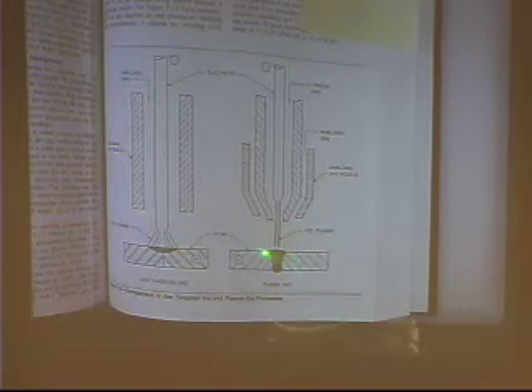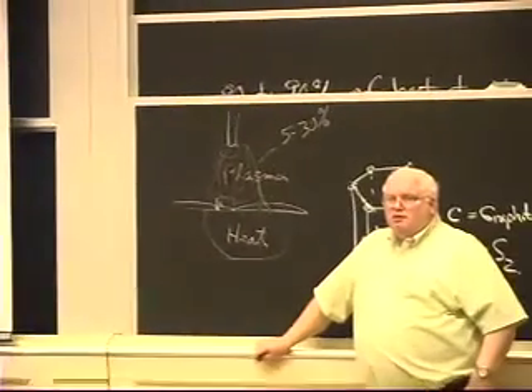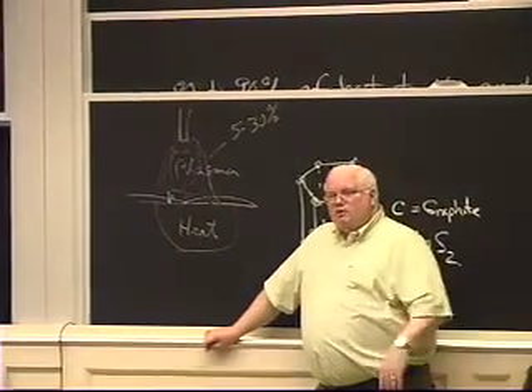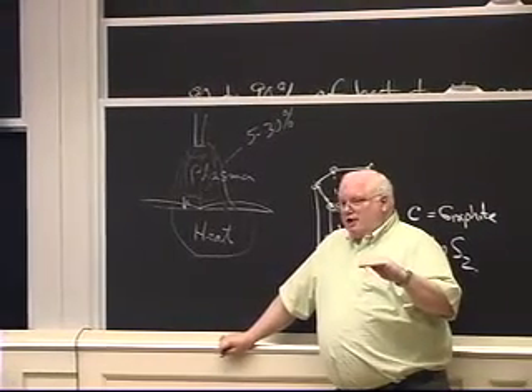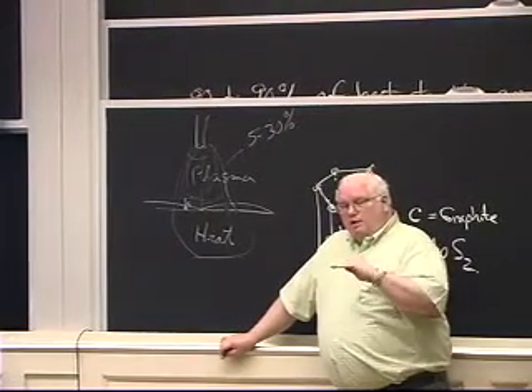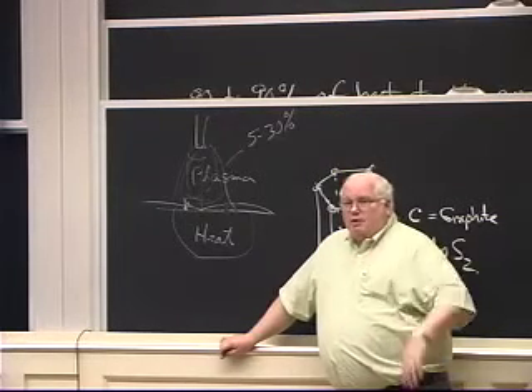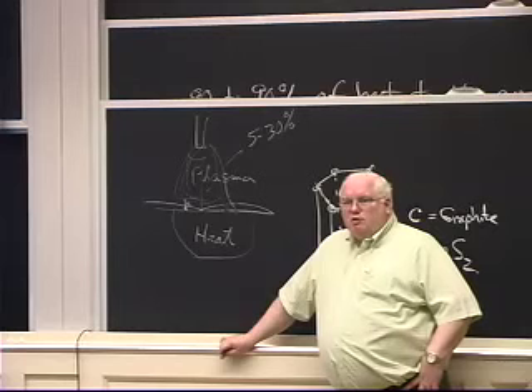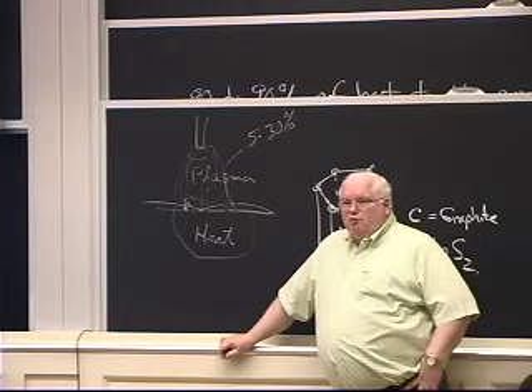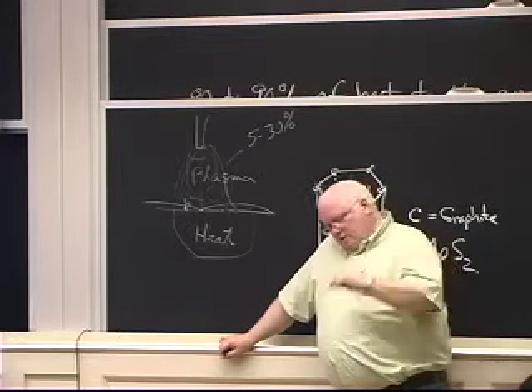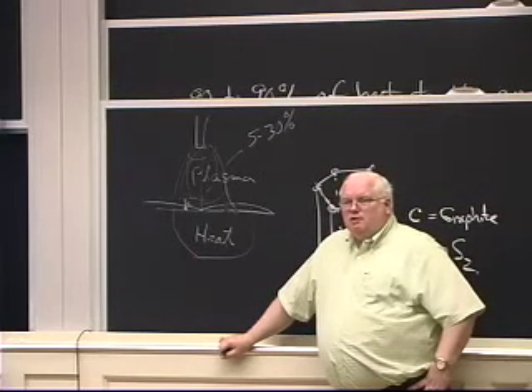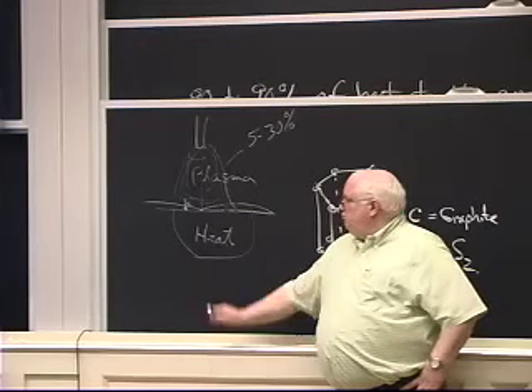You'll get about 2,000 watts per square centimeter in a non-transferred plasma arc where you don't have any current going to the workpiece. If you do the exact same thing and most of your current is going to the workpiece, you'll get 10 to 20,000, because 90% of the heat is carried by the electrons. You'll get 10 times more heat transfer when you have those extra electrons carrying the heat into the metal. You can heat up ceramics with no current going into the ceramic, but it's only like a very good flame. If you carry electrons into the metal, all the heat of those electrons gets deposited in the metal, 10 times as much heat as you would get from just a hot gas blowing on the surface.